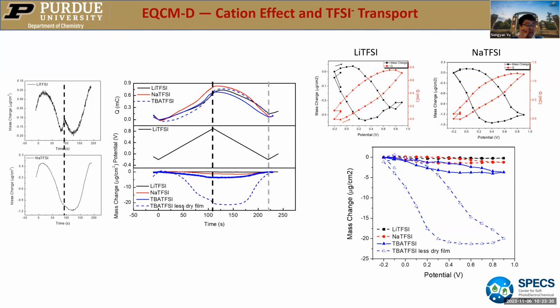I think this can provide us the fingerprint of the ion participation. Even in sodium and TBA TFSI the anion also participated, but because sodium and TBA have a large mass, we cannot really see the TFSI contribution by eye. There may be a small two-step here, but we are not able to see it. And also, if we have a less dry film, the mass transport is much heavier. But if we cycle it long enough, it will finally reach the same level as the dry film.